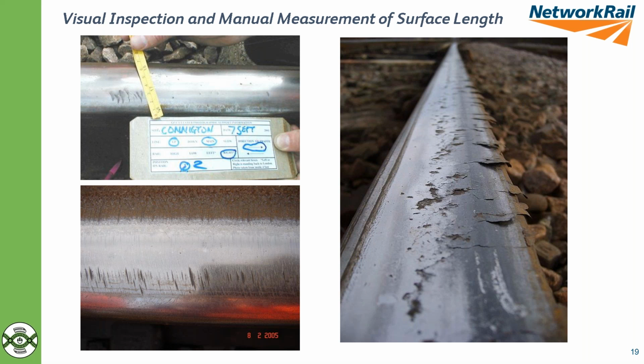And the bottom left picture I've included really not cracks, grinding marks, residual grinding marks left from where the rail has been reprofiled, but often difficult, particularly where they coincide with the RCF. Very difficult then to pick any cracking in or to measure anything. So it's one of the challenges of what we could try and do to be more effective at finding the RCF, how we could manage it better.